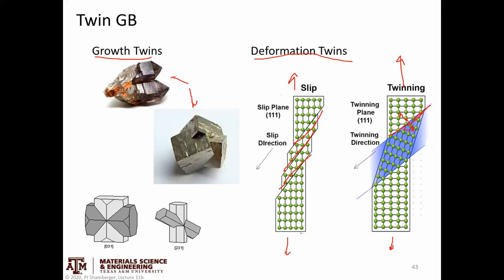Because this lattice has different unit cell lengths in one direction from another, creating a pair of twin boundaries reorients the crystallographic lattice between those twin boundaries and causes extension of the single crystal. That could accommodate the tension being applied. As additional tension is applied, this grain boundary can continue to move downwards and the twin boundary can continue to move upwards, continuing to elongate the crystal. So deformation twins are things that happen in response to a mechanical load.